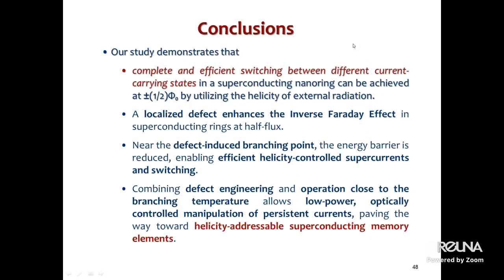No. Originally, we investigated the switching effect in a clean sample. And then a question appeared, because defects are unavoidable in the system, especially in such a small system. So we started to investigate the influence of defects. And then some bistable system appeared. In one situation, the switching effect is totally destroyed, not the current, because two effects were interesting to us. One is switching for the quantum computer, and another one is simply linear response. Linear response is perfectly working, but switching basically was killed. And then we started to investigate and realized that the barrier between these two states disappears after a certain threshold, as I said, the branching point. And then one has to deal with two situations.